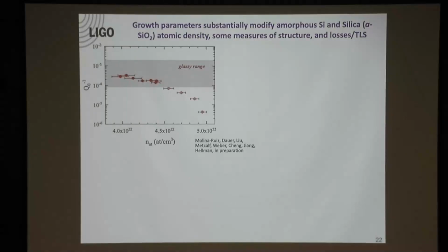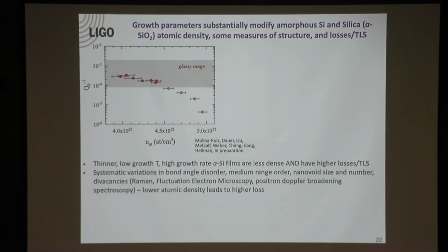Okay, I'm going to cut to the last slide and then conclusions. We've done an interesting thing from the fundamental physics standpoint already, which is that we are able to prepare amorphous silicon not just in this low-lying state, but in a whole range of states. And when you prepare in a whole range of states, we end up with a range of atomic densities and this remarkable plot showing the Q, where it starts off very low, grows exponentially, and then saturates in that universal range. So it is possible that we have solved the problem of what the universal range is about. We believe it's about when there are enough of these tunneling states that they start interacting,